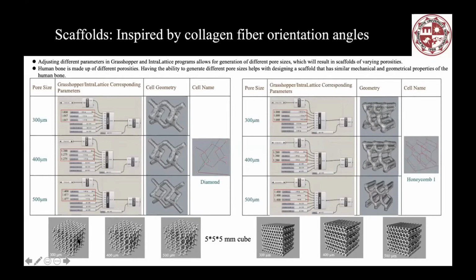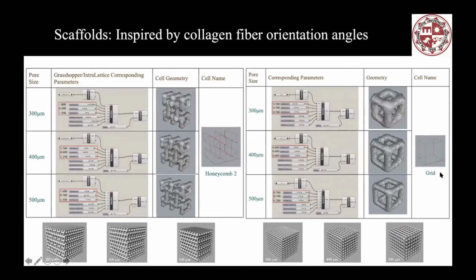Because human bone is made of different porosities, with this software we give the ability to generate different pore sizes to design a scaffold. They have similar mechanical and geometrical properties to human bone. So eventually we focus on these 12 different scaffolds, with different pore sizes and different geometry, like diamond, honeycomb 1, honeycomb 2, and the grid. So this is the different one. And for each one, they will have different sizes. So eventually we'll have 12.